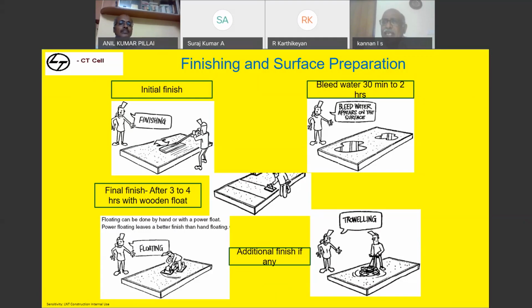Suppose your slab is having a secondary finish of flooring or something, better to go for a broom finish. Don't insist on a trowel finish because trowel finish will induce a lot of cracks. The smoother the surface, the cracking tendency will be much more. Unless it is warranted, don't insist every slab needs to be finished with a power trowel. If you have a floor finish or something, better to go for a broom finish, make the surface rough, so that you are avoiding the concrete from cracking. That is one.